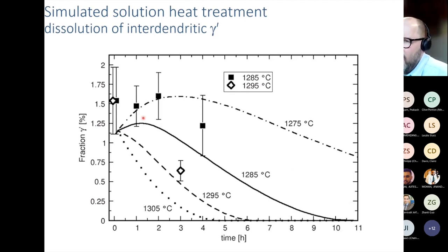with this graph. So here the closed symbols correspond to the solid line and the open symbols to the dashed line. We find that initially upon heating up, the gamma prime is not dissolving very quickly. So I should say the lines come from the simulations, while the symbols come from some experiments. The error bars look huge, but this is the standard deviation of determining the gamma prime from the micrographs. And the gamma prime fraction is not very large. We find this is about 1.5%.